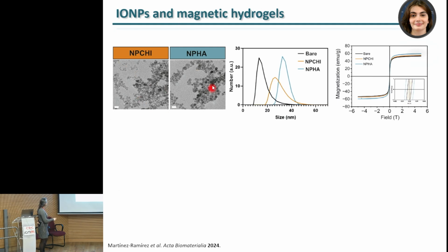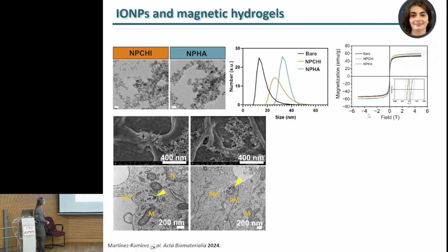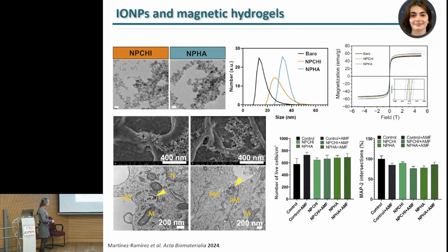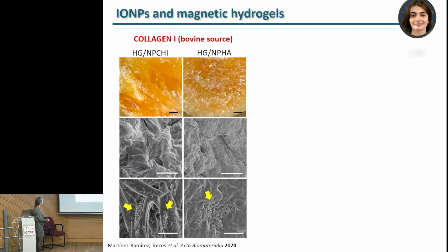Specifically, she selected chitosan and hyaluronic acid. These are two biopolymers with a lot of properties that are beneficial, and particularly beneficial in neural tissue engineering. So you have here the characterization and the magnetic properties that are not affected by the coating, and then the interaction with the cells. You see here again a very close interaction of these iron oxide nanoparticles with the different neural components, and again we could find them, both of them, inside the cells. We also checked viability, the differentiation into neurons, into astrocytes, and there were not significant changes.